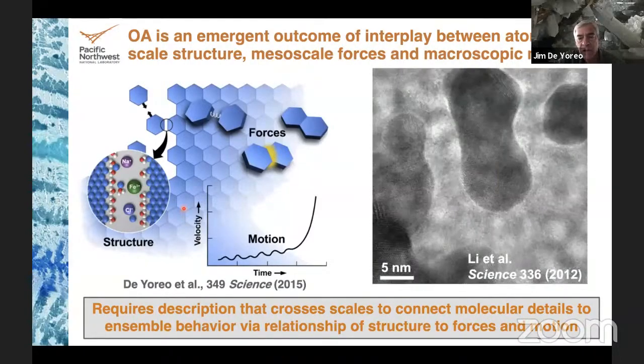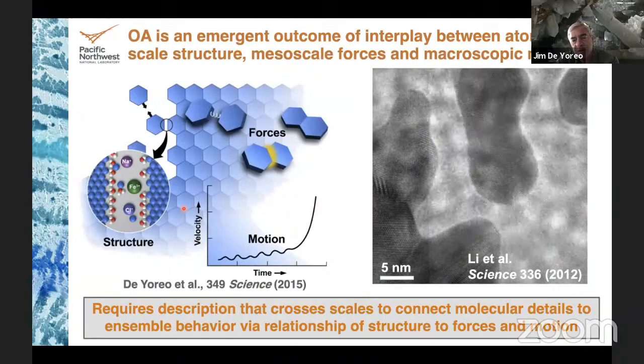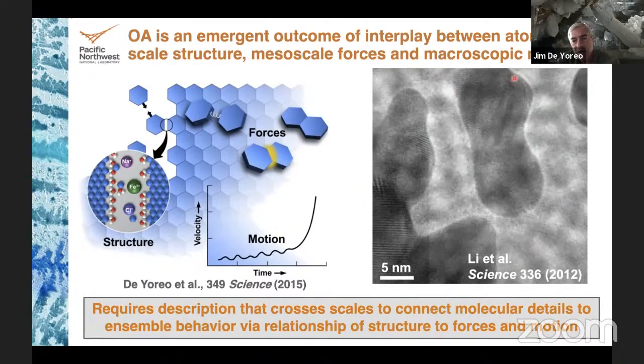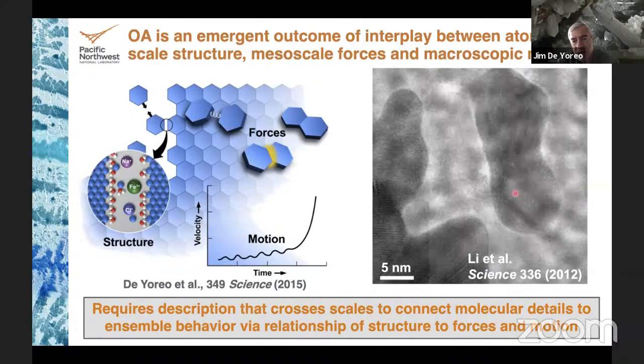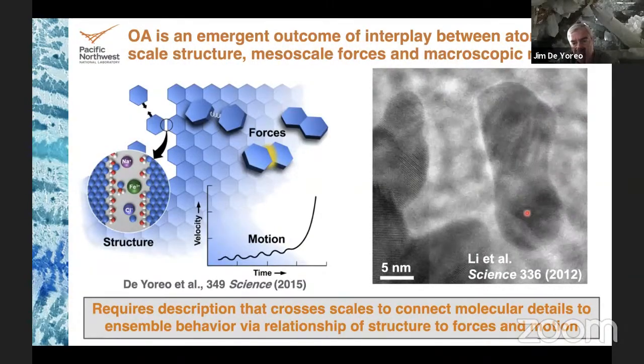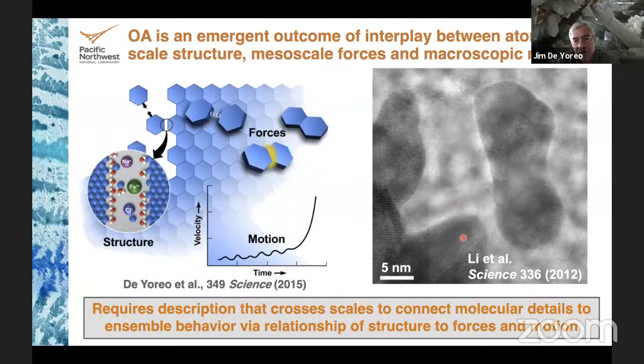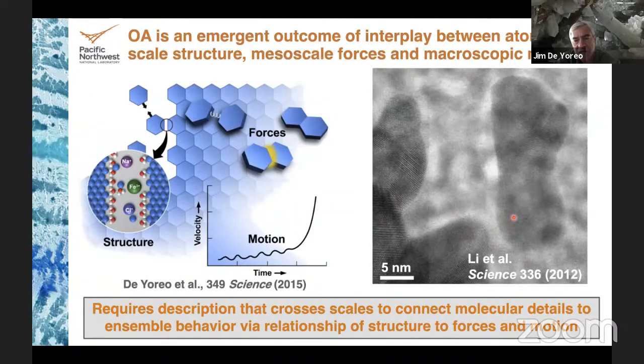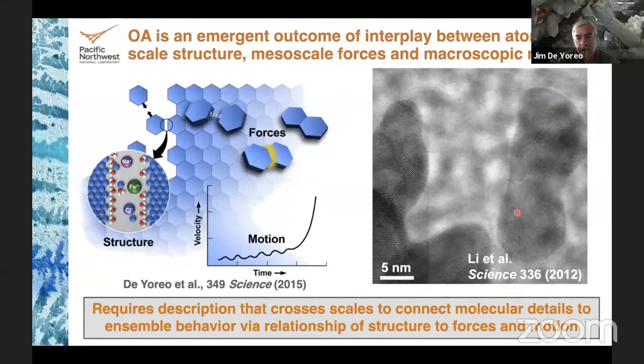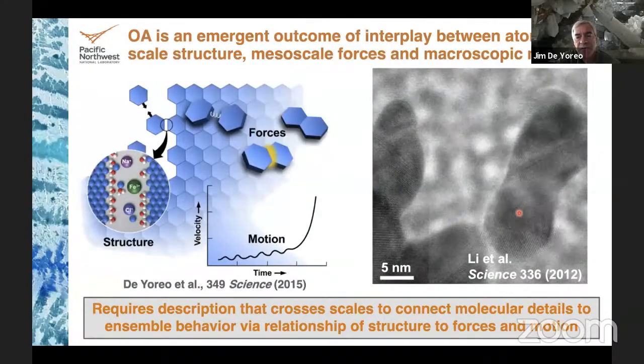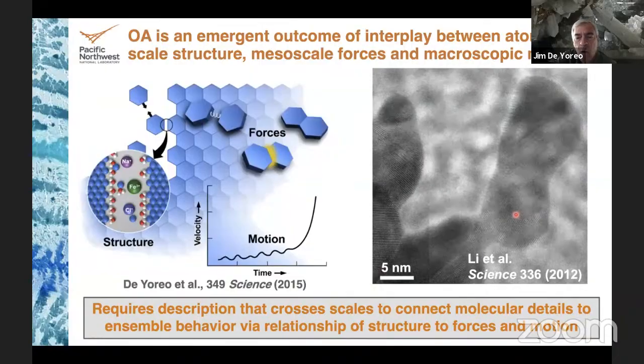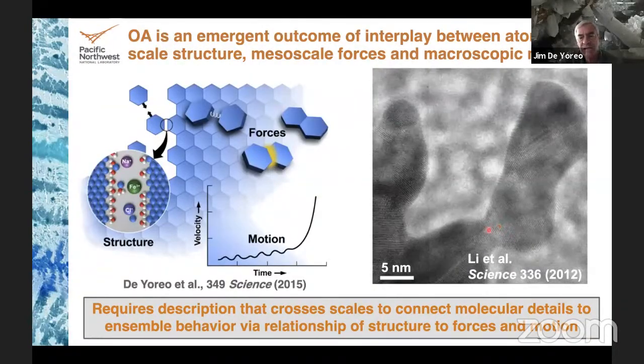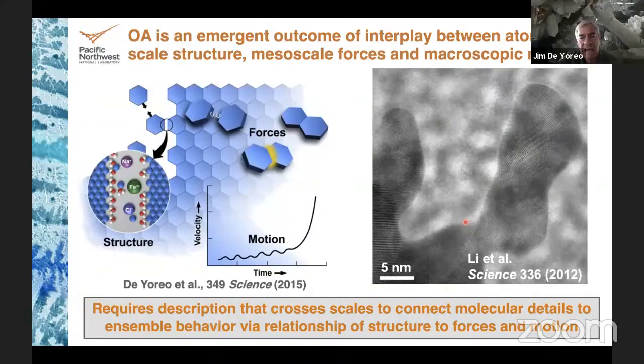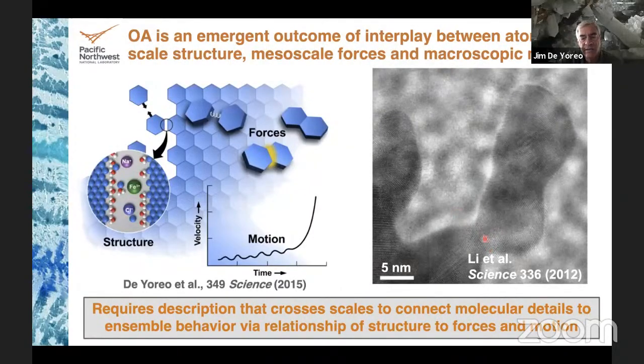Now, here's a nice TEM movie we did some years ago showing aggregates of particles already formed through oriented attachment. This is an iron oxide system. And you can see as a particle drifts by, it suddenly realizes there's another particle very close, and it stops in its tracks, rotates until it's co-aligned, and then it jumps to place. Now, it doesn't have quite exact alignment at the moment of contact, so you can see it slightly rotate back again, healing the defects, the edge and screw dislocations that existed at the interface initially. But in the end, it's a perfect attachment.